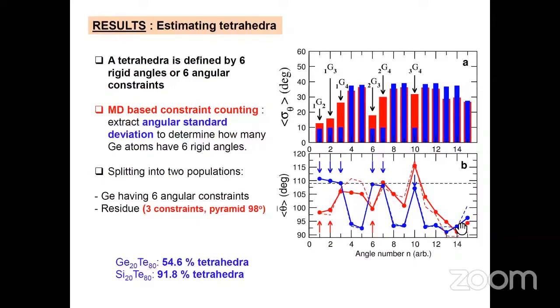So from the trajectories that we obtain, we don't look at angles, but we look instead at angular excursions. And if we are able to identify around a central germanium atom 6 small angular excursions around that atom, then we're sure that we have a tetrahedron. So on the first panel, we plot as a function of the angle number the variance of those local angular distributions. And we can see that for the blue bars, we detect 1, 2, 3, 4, 5, 6 angles which have a low standard deviation, which means they have low angular excursions, and this is a signature of tetrahedra.